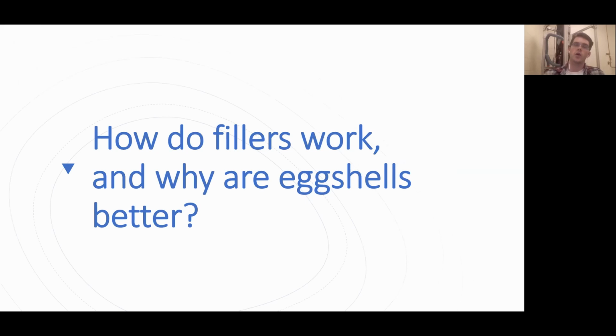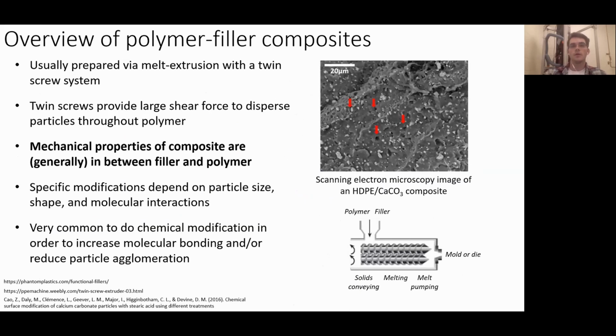I want to start off by giving a quick overview of how these polymer filler composites are made, their mechanical properties, and then move on to what the eggshells themselves can offer as a polymer filler. So these polymer filler composites are generally prepared using melt extrusion with a twin screw extruder system. The polymer and the filler are fed simultaneously to a hopper. And the two screws actually provide a pretty significant amount of shear force, which allows for good dispersion of your particles throughout the polymer. Then the composite is extruded through a die or into a mold to form whatever product you want out of the composite.